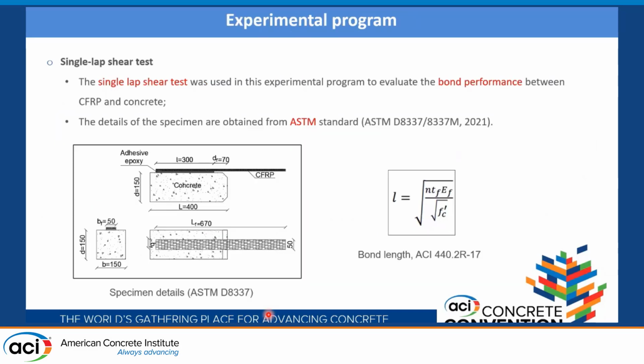The single lap shear test was used in this experimental program to evaluate the bond performance between CFRP and concrete. The details of the specimen are obtained from the ASTM standard. As shown in the left figure, the concrete block dimensions are 150 by 150 by 400 millimeters. The width of the CFRP strip is 50 millimeters. The bond length is equal to 300 millimeters, where the effective bond length is obtained by the equation on the right, by ACI 440.